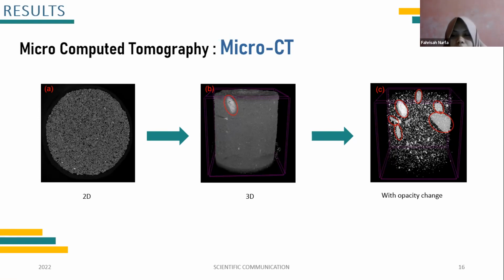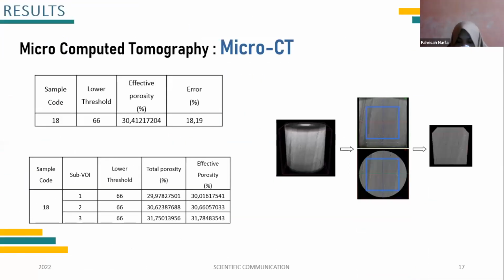This will select the area according to the brightness level. Figure C shows an area with a higher brightness level with opacity change, which means it has a high density. As it turned out, there were many areas of large grain size at the top of the sample image. In microCT,